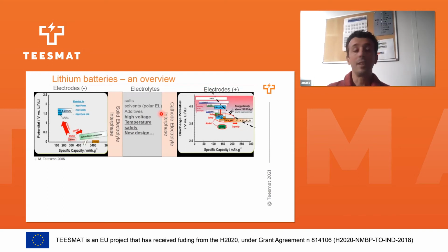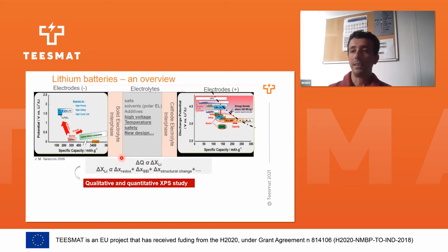A lithium-ion battery is very simple, but at the same time it is a very complex material system. It's simple in the sense that a negative electrode is linked to the positive electrode through an electrolyte, and we have ionic exchange. That is the simplest part of the lithium-ion battery. But the complexity depends on the redox couple that we build. As we can see, on the anode side, the low voltage materials include lithium metal, carbon, silicon, LTO, and for the cathode, the positive electrode, we have different families. Depending on the redox couple that we build, the problems, the phenomenologies and the processes will be different. So there are many parameters that link the capacity loss of the chosen system to the performances.